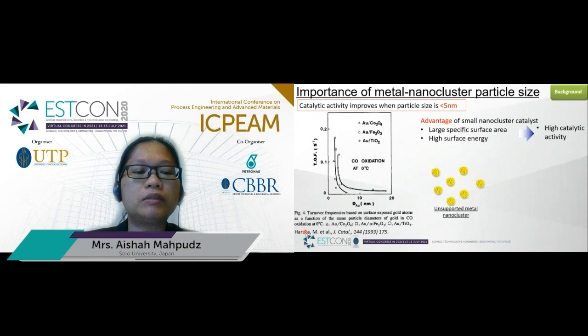For example, a landmark research done by Haruta and co-workers in 1993 has shown that the catalytic activity of a supported gold particle increases with a decrease in particle size when it is used as a catalyst in carbon monoxide oxidation reaction. This is because compared to the larger particles, small nanoclusters have a larger specific surface area as well as high surface energy, contributing to the high catalytic activity.